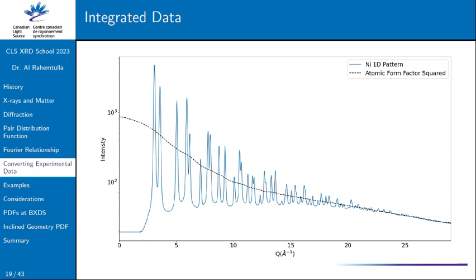Okay. Yep. I could add a different sort of explanation. When you have a collection of electrons in an atom, then you're having scattering off that atom, since it has a size, and you're going to get scattered from different parts of the atom, and therefore you get partial destructive interference. Because the atom isn't like a tiny little point compared to the wavelength. So if it scatters off one part of the atom or another part of the atom, that scattering isn't completely in phase, so it's partly destructive. And how destructive it is depends a lot on the angle of the scattering.